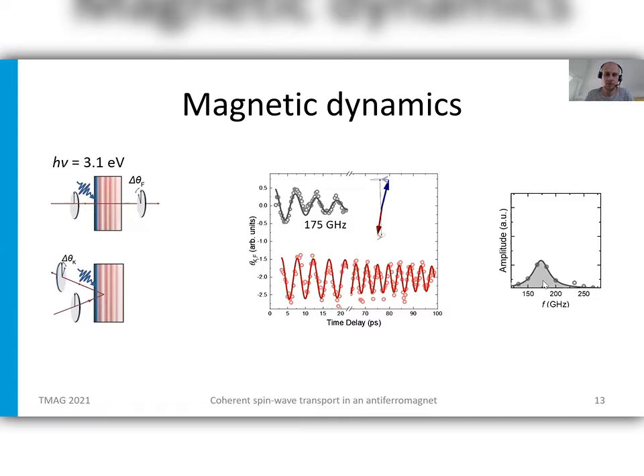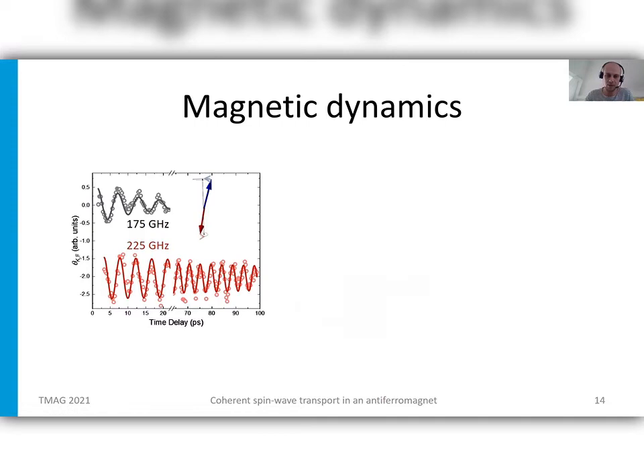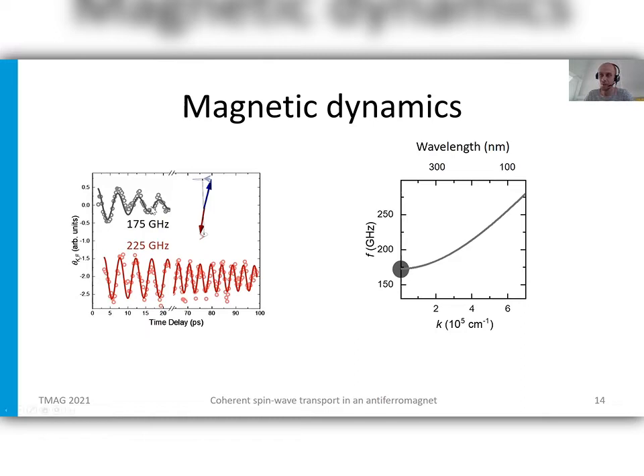By looking at the reflected probe light, we also get an oscillatory signal in time. However, the frequency of this signal appears to be larger, so we're looking now at a 225 gigahertz signal which is almost 50 gigahertz larger. With the idea of the specific geometries in mind and also with the dispersion relation, we can easily explain this. The first experiment is sensitive to a uniform antiferromagnetic spin precession, so a spin wave with wave number zero basically. In this reflection geometry we're actually probing a spin wave with a wavelength of around 140 nanometers which has a frequency which is around 50 gigahertz larger than the Brillouin zone center magnon. This is indeed a propagating spin wave in this antiferromagnet, generated and detected optically.